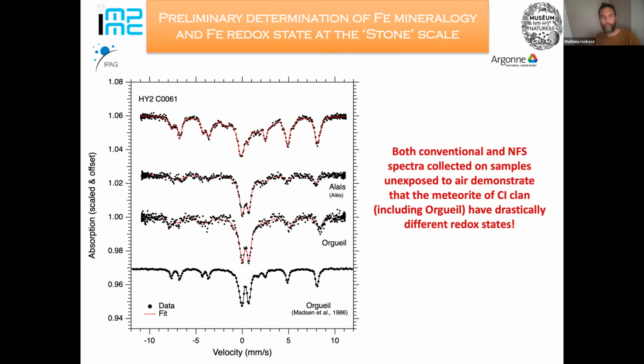But if you look at the Mössbauer spectrum, and here I just compare the conventional Mössbauer spectra because we are all more used to this kind of spectra, you can see that there is a huge difference. If we look at Orgueil and Ivuna, there is something like 90% of the iron present in clays that is oxidized. Actually, it is known that it's not really clay, it's ferrihydrite. So, most of the iron present that is not in magnetite is present as 3+.